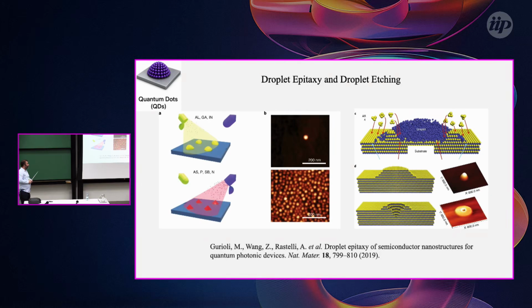Okay, here everybody is an expert in droplet epitaxy, and basically, you can deposit a group 3 element on top of, let's say, gallium arsenide. This element will form droplets on the surface, and if you control the exposure of these droplets to group 5 elements, let's say arsenic, and control the temperature of the substrate, you can form these gallium arsenide quantum dots. Or if you change the parameters again, you can also start etching the substrate, and you can make nano rings, or what I was working on for the last 7 years, what we named droplet etching quantum dots.